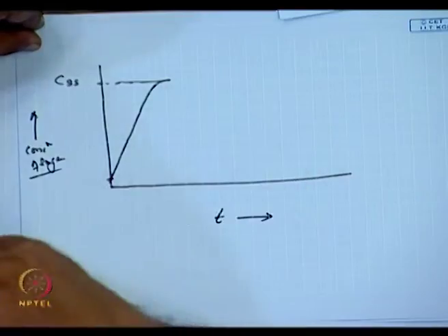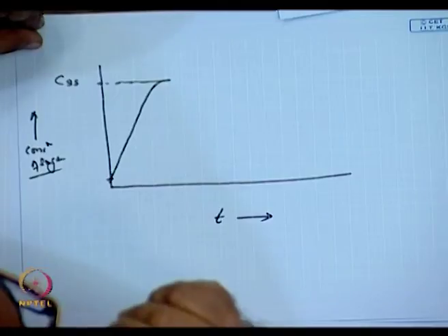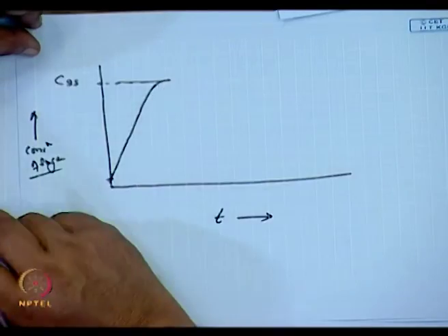Let me label this as concentration supersaturation. At this point, if I keep on heating, what would happen? Sugar would start precipitating out. Why? Because it is already supersaturated, the solution cannot hold any more sugar, it will come out. Now, let me hold the whole solution at that particular temperature and time when I have just reached supersaturation level.